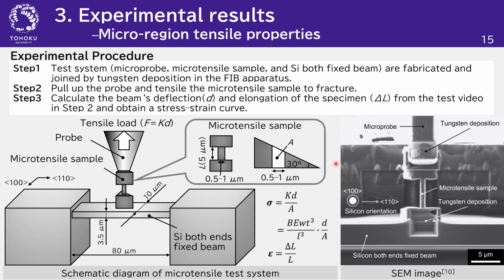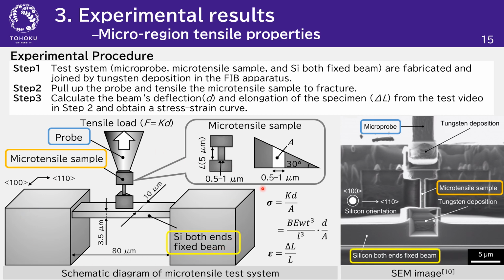In this experimental procedure, a probe, a microtensile sample, and a Si both-ends-fixed beam are fabricated in the FIB apparatus, and then each element is bonded by tungsten deposition. The sample is formed to a width of 0.5 to 1 micrometers and a length of about 5 micrometers. Next, the probe was pulled in the tensile direction until the sample broke.